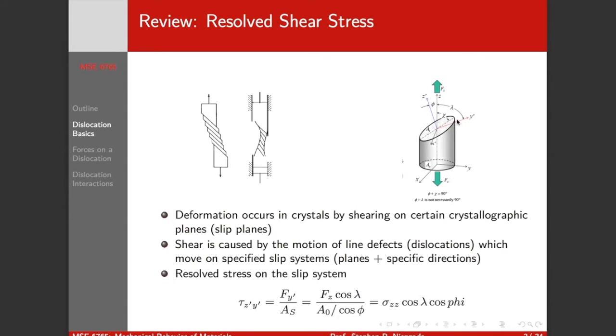Or the double dot product of the slip direction, the plane normal and the slip direction of the stress tensor. And so if we imagine two angles, phi, which is the angle between the tensile loading axis and our slip plane normal, and lambda, which is the angle between our loaded tensile axis and our slip direction,